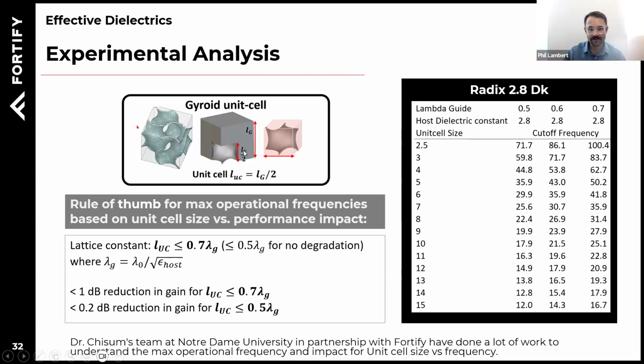And we're going to call that LG over 2. And so we have this unit cell constant that we're calling LUC here. So that unit cell constant is LG over 2. And so long as you maintain a rule of thumb representation of this unit cell equal to 0.5 of the wavelength of your frequency when it's guided within that dielectric, you will have a nearly perfect effective medium. And so here's the way you would read that.